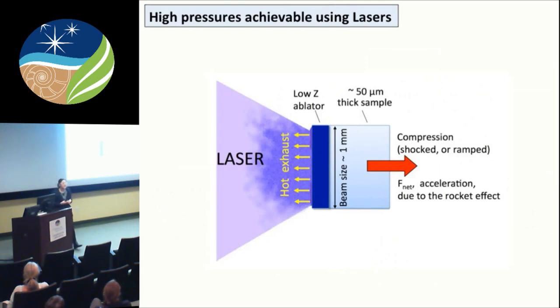How do we achieve high pressure using these lasers? Similar to laser ablation ICP-MS, these lasers are focused onto a surface — often something low-Z like diamond or plastic that's easier to turn into a plasma. Creating a plasma with a high-powered laser immediately produces a plasma that expands backwards, sending a pressure wave into the sample — equal and opposite effect. Using lasers, we can actually replace typical ways of getting high pressure and send shock waves or any pressure rate through our sample.